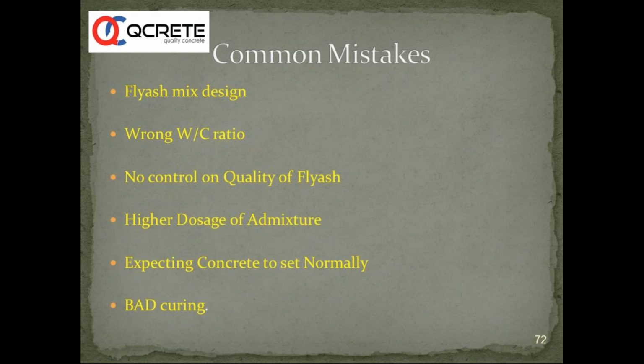A manufacturer also guarantees the density should not deviate plus or minus 200 kg per cubic meter. These are some of the specifications I took from BS EN 450-1. So here, the manufacturer or the seller or the transporter of fly ash is guaranteeing some of the characteristics or properties of fly ash, and you can blindly use such fly ashes. But unfortunately in India, many of the manufacturers and transporters simply transport the fly ash from the thermal power plant to a cement company or ready-mix company, and it is left to these users to take care of the quality, and there is no guarantee from the manufacturer.